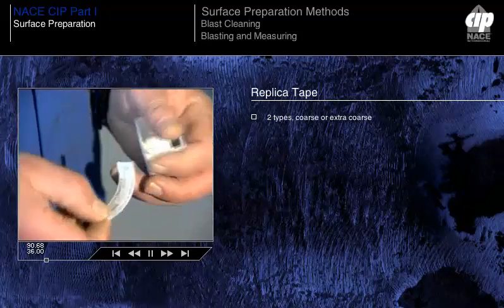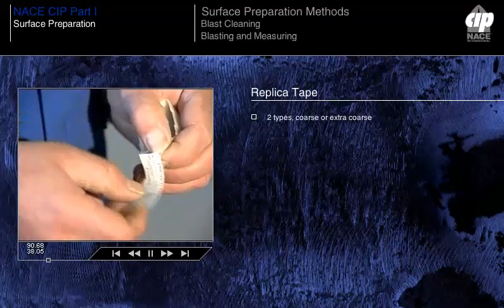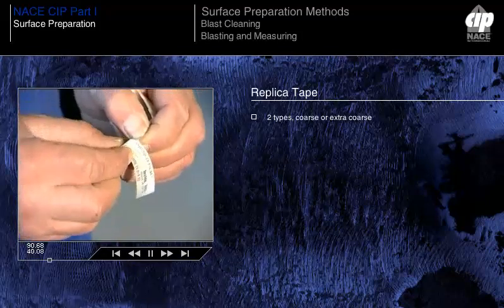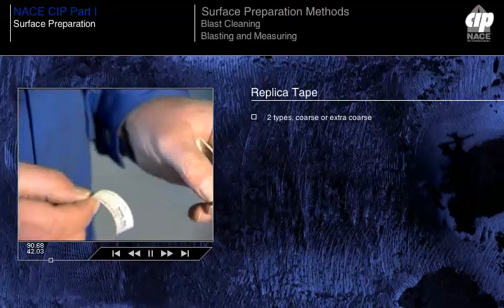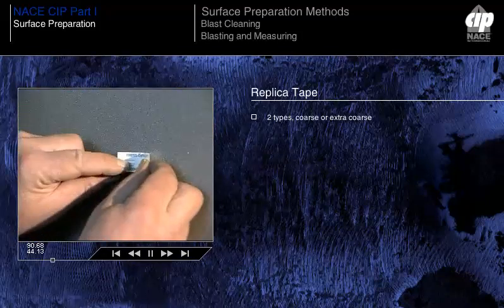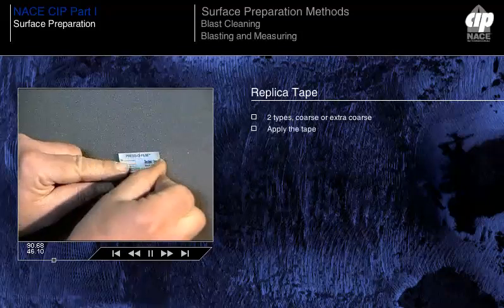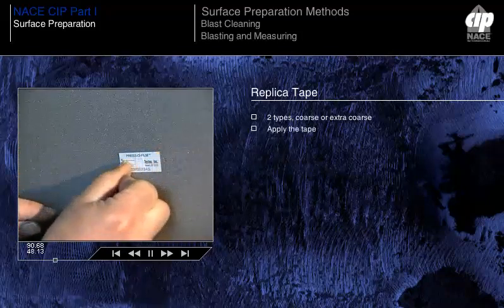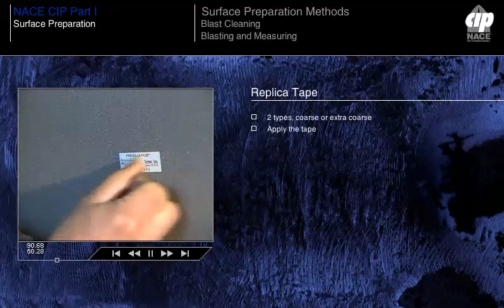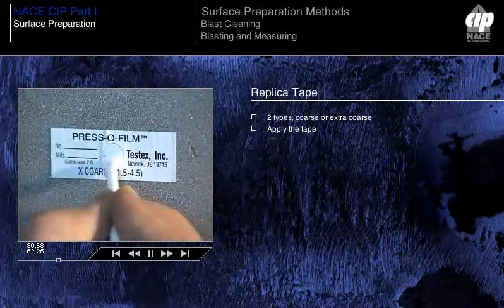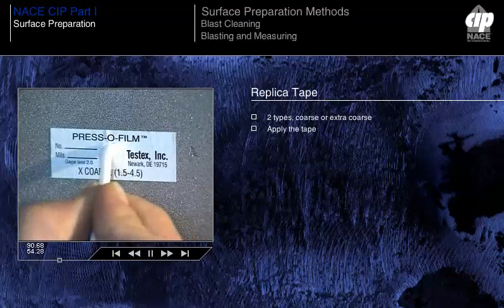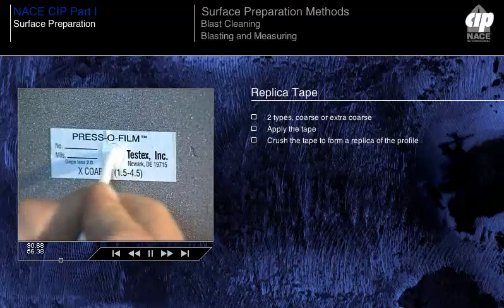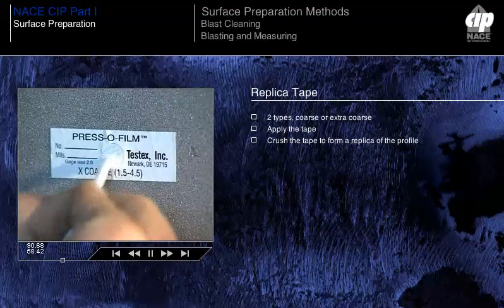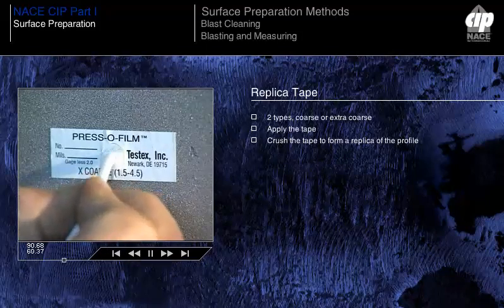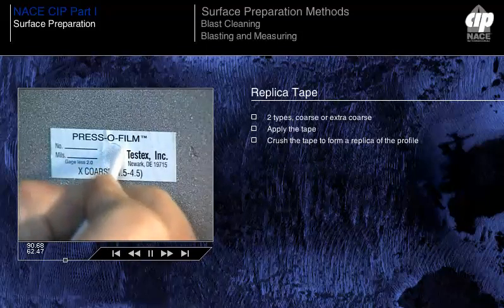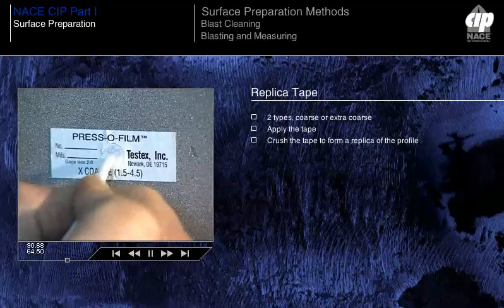A piece of tape with a small square of compressible foam plastic attached to a non-compressible plastic mylar film is applied to the blast clean surface, dull side down. A hard, rounded object, a burnishing tool such as a swizzle stick, is then used to crush the foam to the blast clean surface, causing the foam to form an exact reverse impression replica of the actual surface profile.